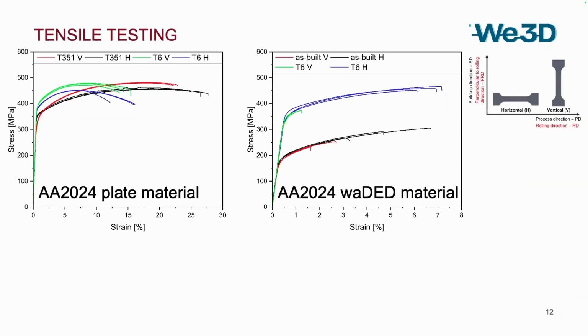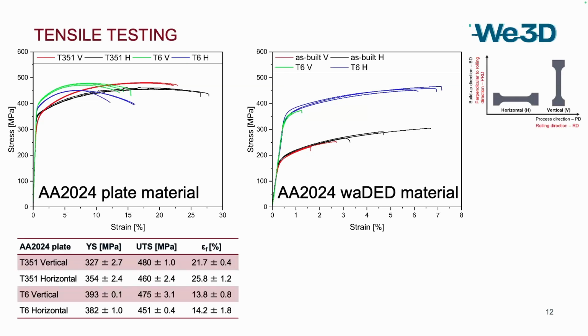Now we switch to the results. Let's start with the tensile tests. On the left side, the plate material in the conditions T351 and T6 with both vertical and horizontal orientations. Basically, we have one difference in the conditions, the reduction of the fracture strain from T351, which is about 22 to 26%. In T6 condition, we only have 14% fracture strain here.